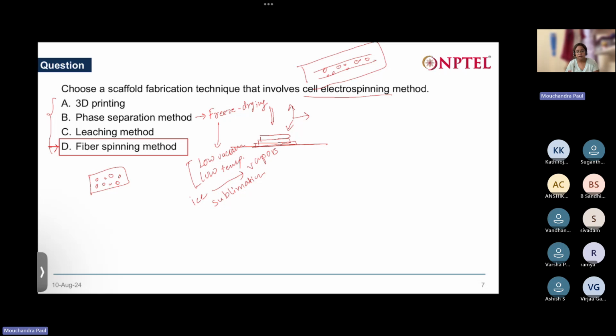One classic example of the leaching method is solvent casting and porogen leaching. You again prepare a solution, say a solution of polymer plus solvent, and you also add a porogen. A porogen can be NaCl salt crystals. You mix it very nicely, and then you cast this solution into a mold. So you have NaCl salt crystals embedded in it. Then you cross-link it.